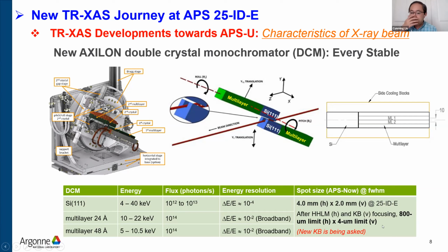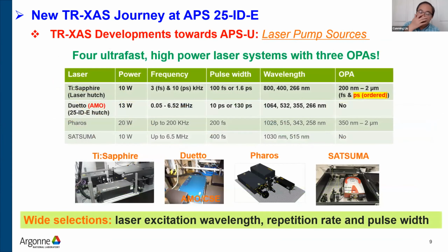Right now, as for the X-ray spot size at the sample position, we can focus the horizontal down to 800 microns, and we can make the vertical size much smaller, 4 microns, with a KB mirror. Now we are ordering new KB mirrors, and we hope we can achieve a much better X-ray beam profile at the sample position.